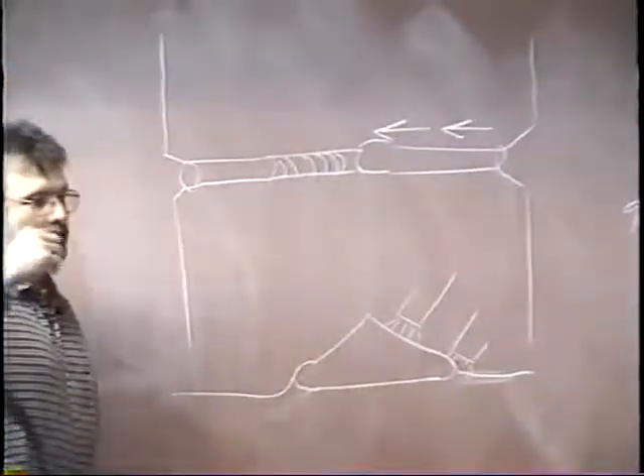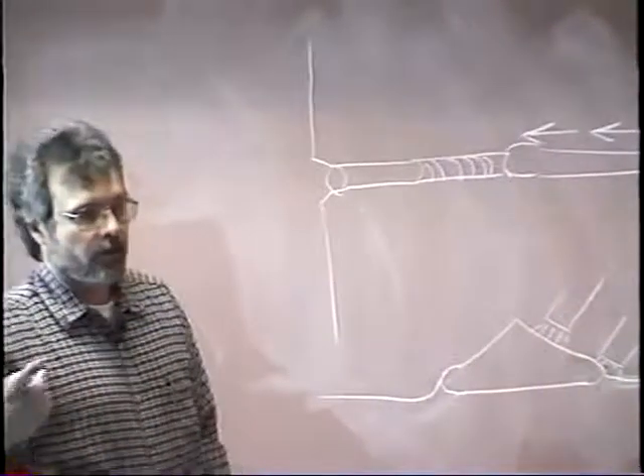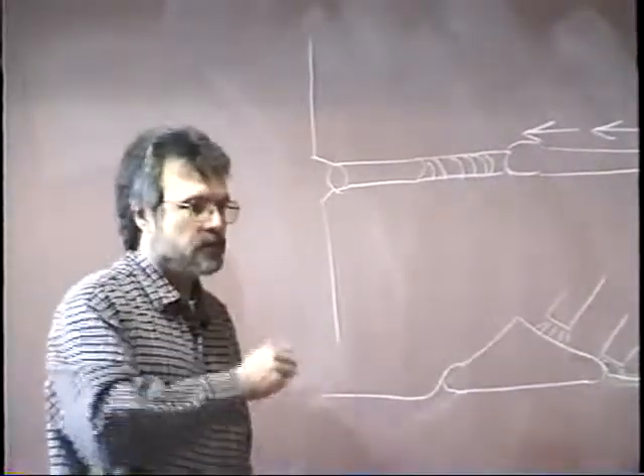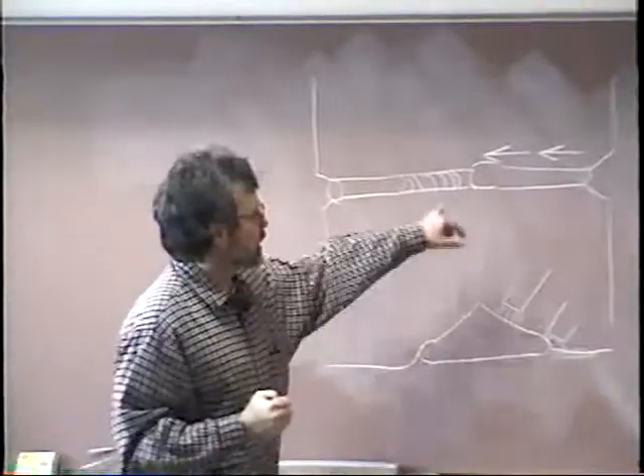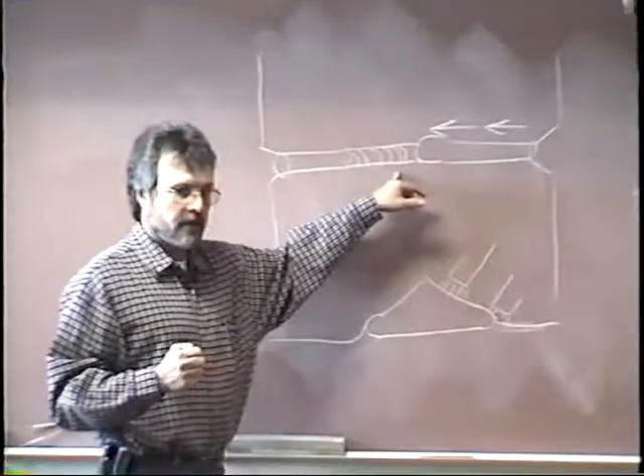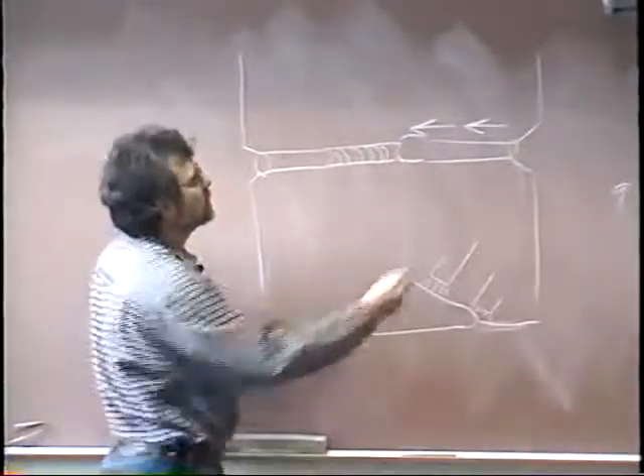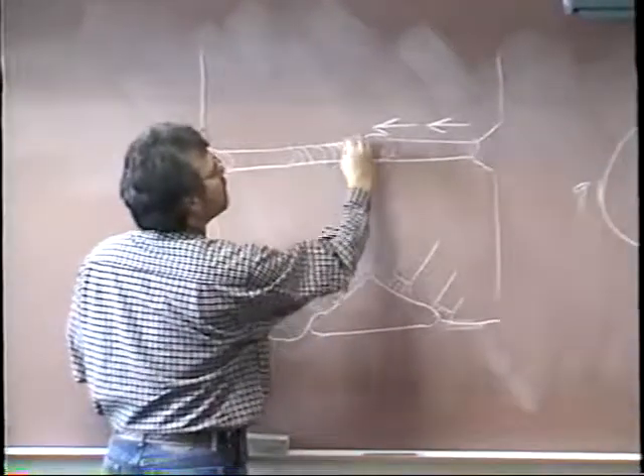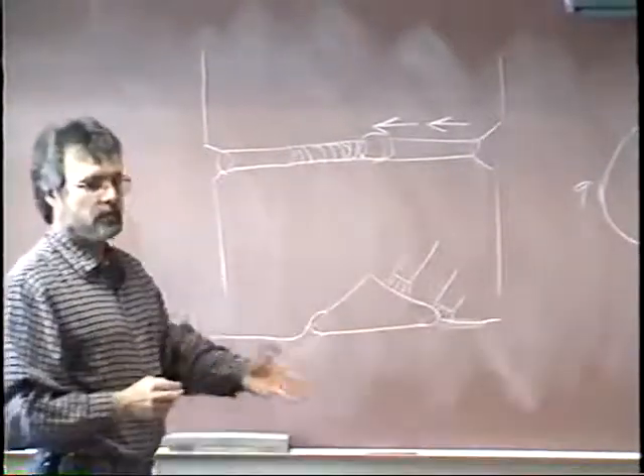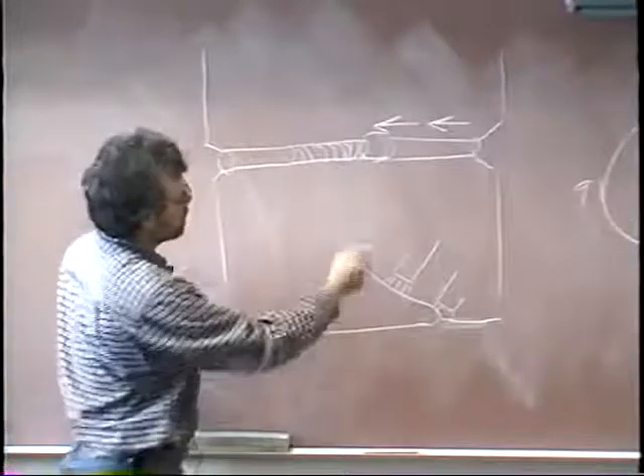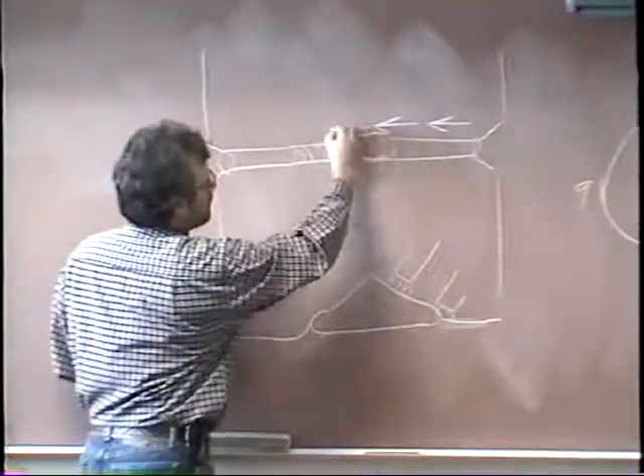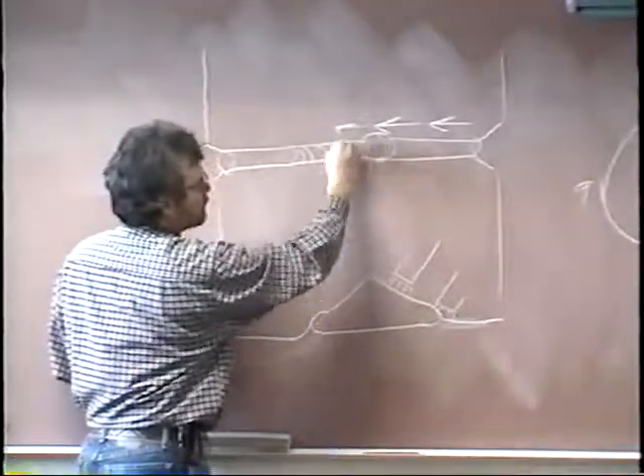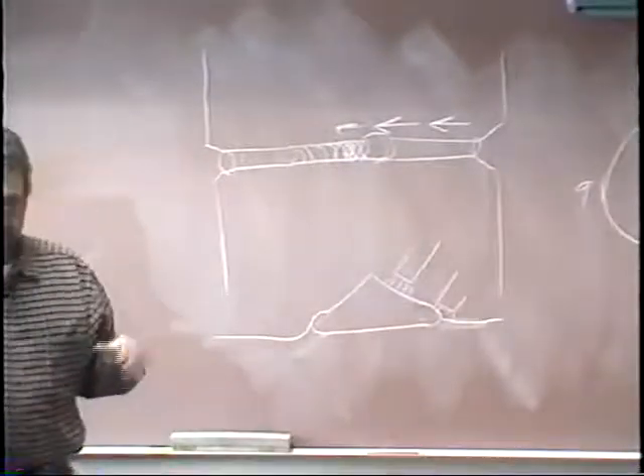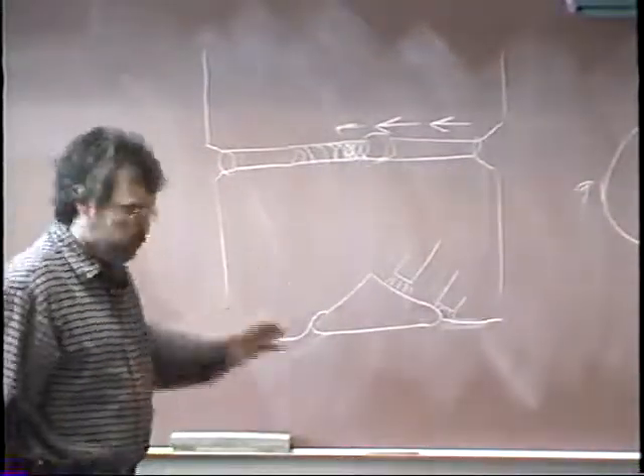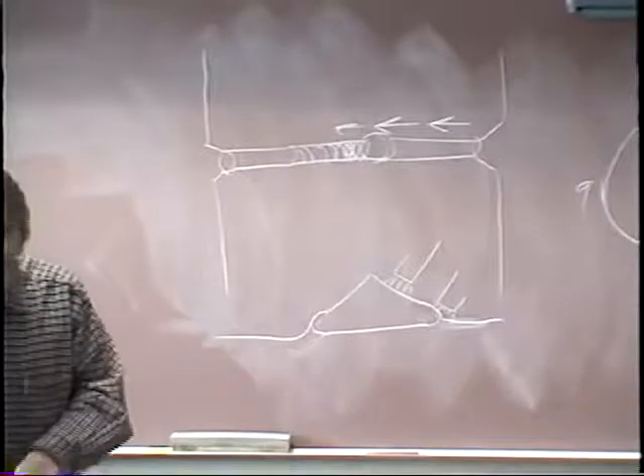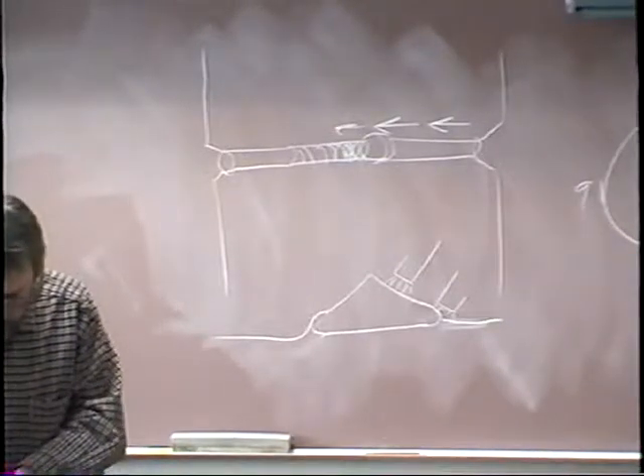So if I've worked with you individually in the welding booth, I've told you not to stop once the sound of penetration stops. When you're tying into a tack, keep welding. We keep welding until the trailing edge of the puddle ties in, not just the leading edge. We want that trailing edge to tie in. By using that whipping technique, we're preheating this so that we get a better tie-in and a better blending. And again, if it's feathered, it'll make a really nice tie-in.